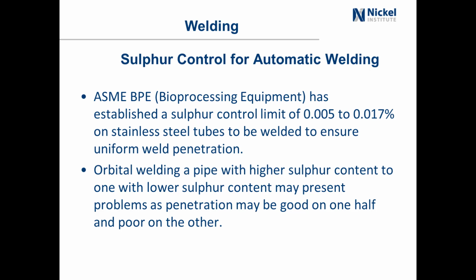So for orbital welding, it's specified that the sulfur needs to be in this range, because the stainless steel industry doesn't like sulfur to be present, because that means you have sulfide inclusions. Sulfide inclusions are places that can be sites for premature pitting corrosion on a stainless steel. So they've done everything they possibly can to get the sulfur out of a stainless steel. So generally it's less than 0.001.